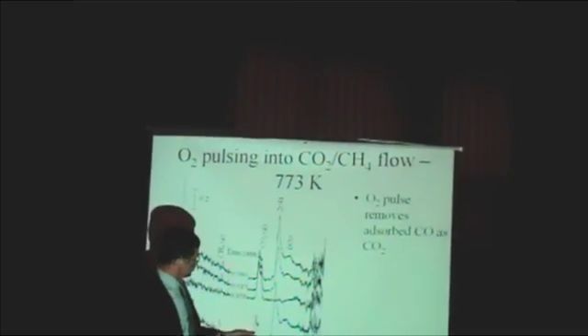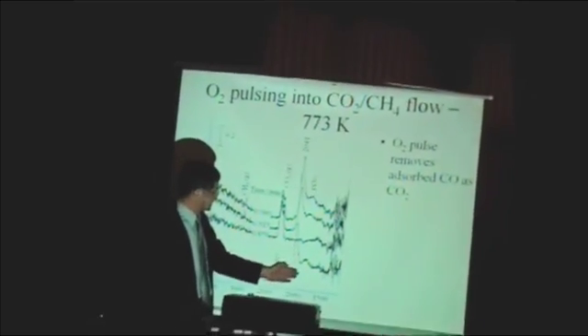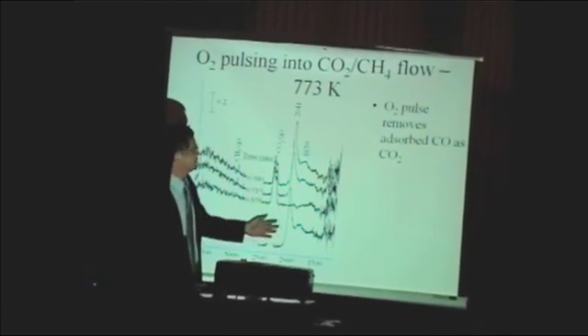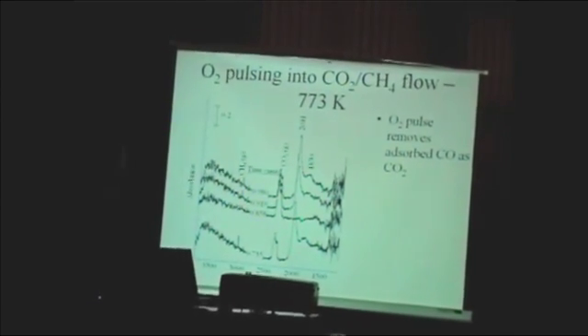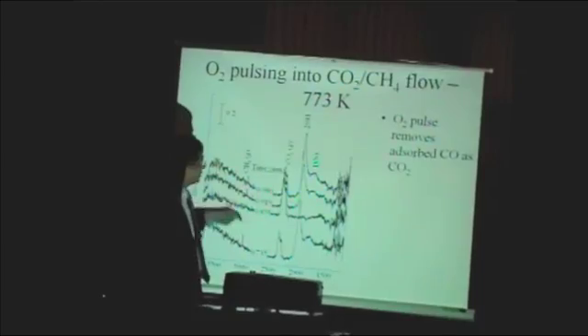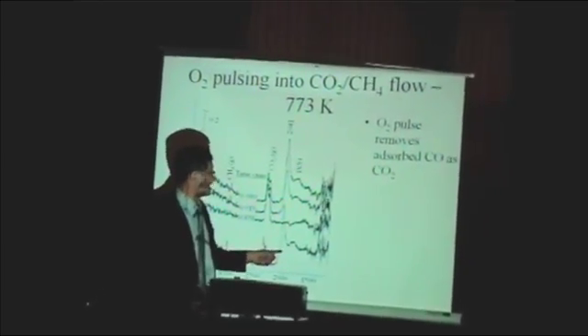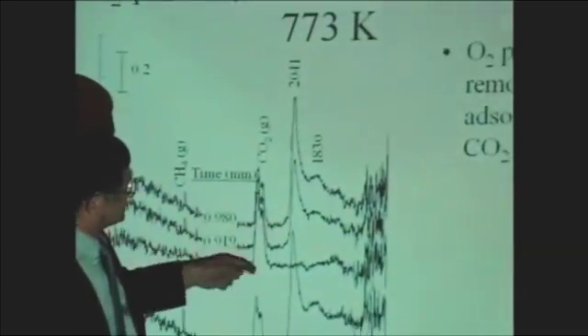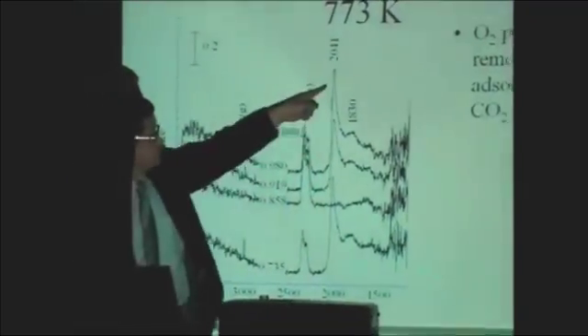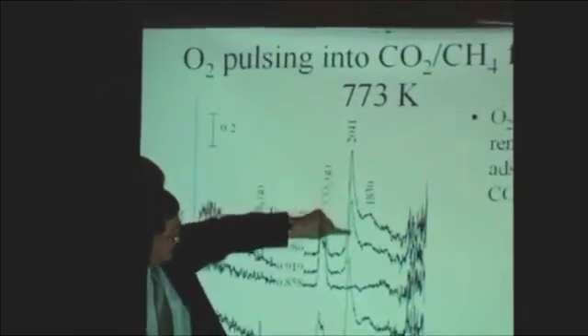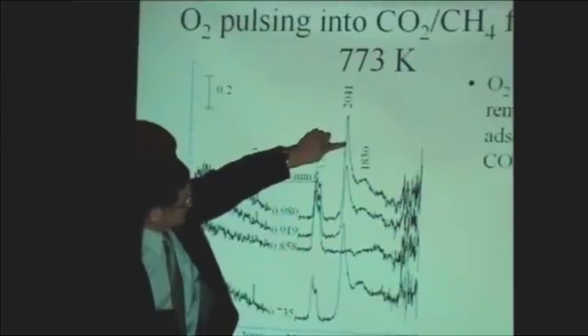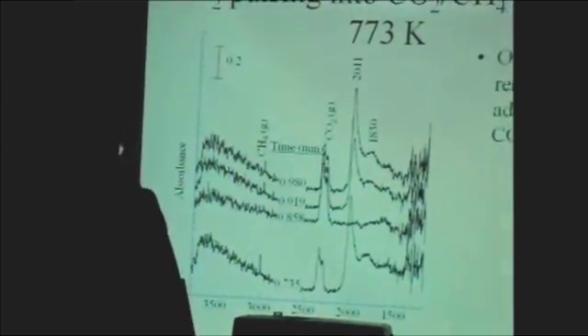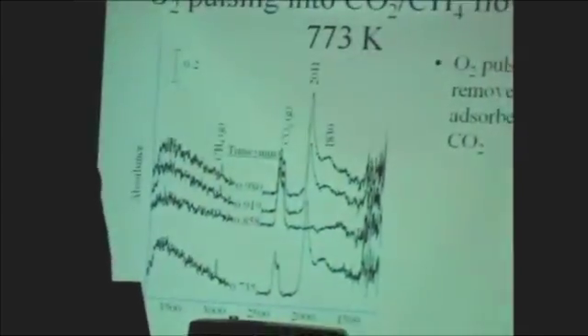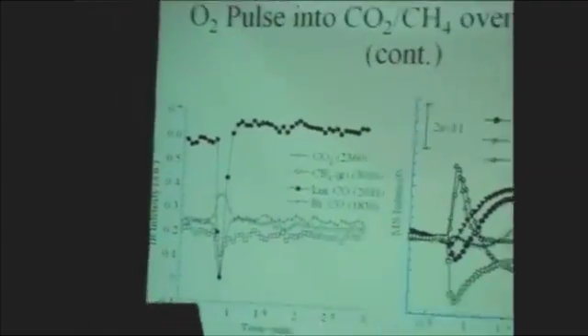So when methane and CO2 wash through the reactor, there are linear CO and bridge CO on the surface already being produced. Then if we pulse the oxygen in, this oxygen will come in to oxidize the adsorbed CO on the catalyst surface. And in fact, this oxygen coming in enhances the formation of linear CO. You can see that this peak here is about 20% or 30% higher than the initial linear CO band here. So the oxygen coming in indeed promotes the formation of CO.